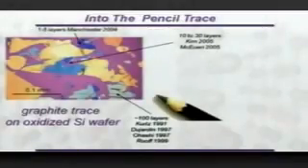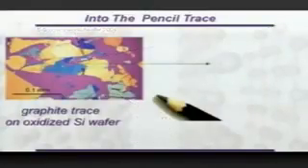Well, quite a few groups, quite a few researchers tried that. What you see here is a pencil trace just done on a special substrate. That purple substrate is silicon oxide, and different thicknesses of graphitic pieces can be seen here as different colors. The whitish are the thickest ones, and the more bluish and more purple it goes, the thinner it becomes. If you try hard, you can probably get to really a single layer, and that's exactly what we've done some time ago.